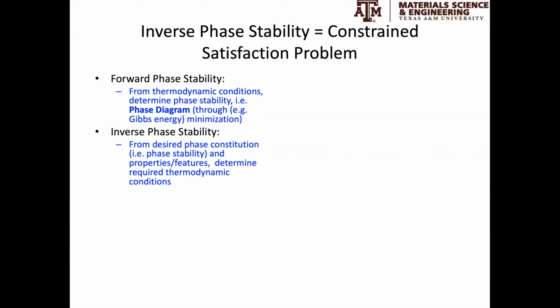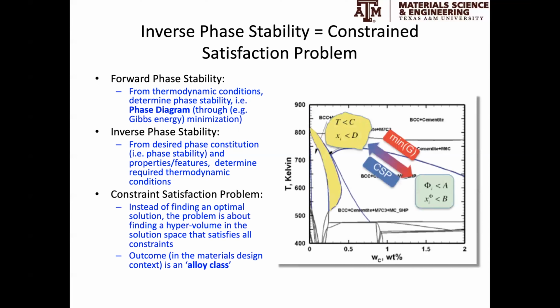On the other hand, inverse phase stability addresses the problem of going from a desired phase constitution. If we want a particular phase to be present under certain operating conditions, can we reverse engineer this requirement in terms of the required thermodynamic conditions to solve this inverse phase stability problem? This is very different from an optimization problem, because here we're talking about potentially just a particular set of phase conditions, like a particular phase with a particular range of chemistries.